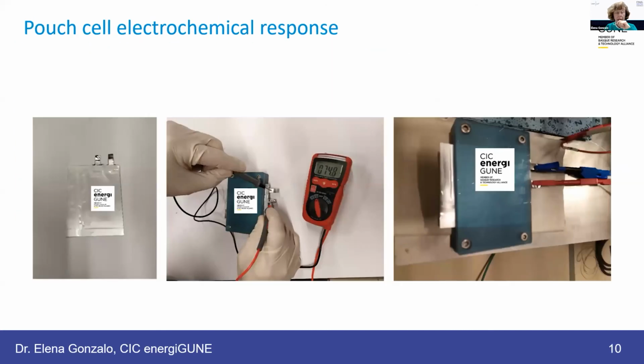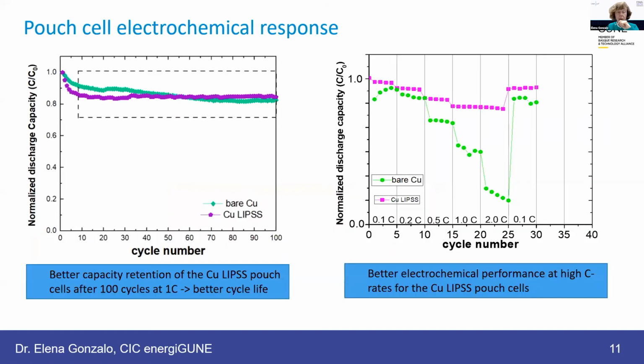So when we have our electrode already characterized, we are able to check the electrochemical response of our pouch cell. So here you have the pouch cell. We check the operation voltage before cycling it, and then we put it in the holders to be tested in our battery testers at CIC energiGUNE. So here you have the electrochemical response of our cells, the comparison between the bare copper foil electrodes and the copper LIPSS. I will show you only these two tests. Of course, we have done several tests in many different cells.